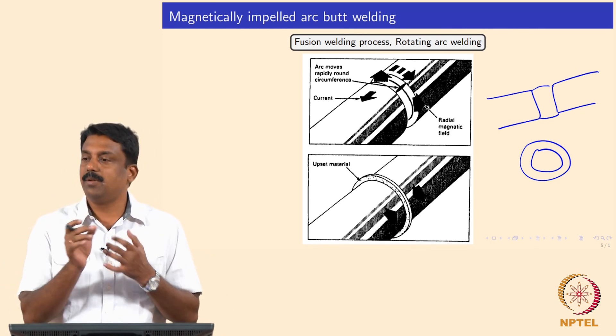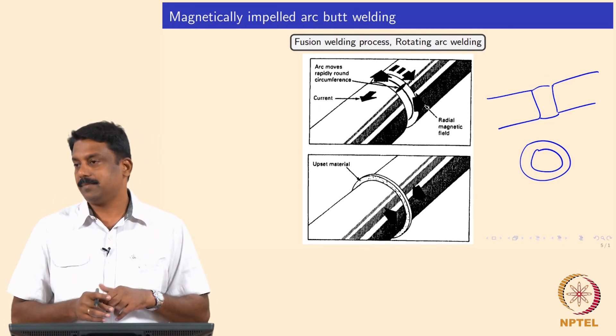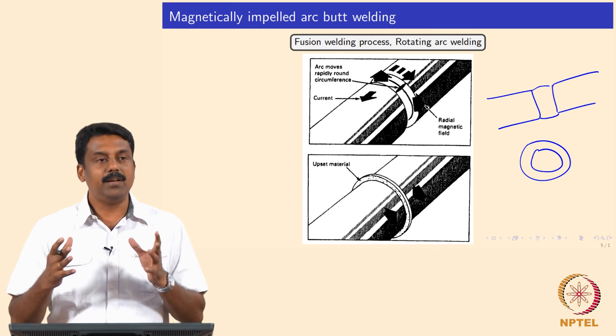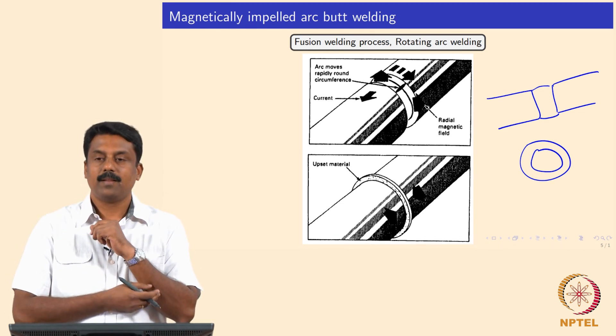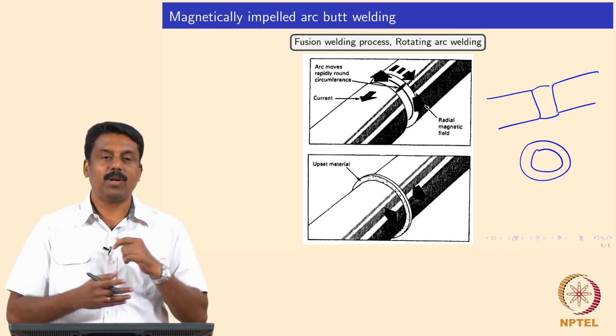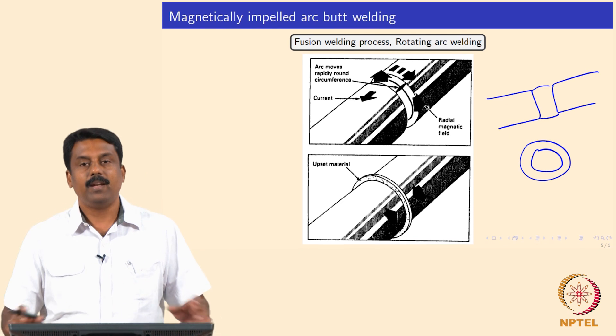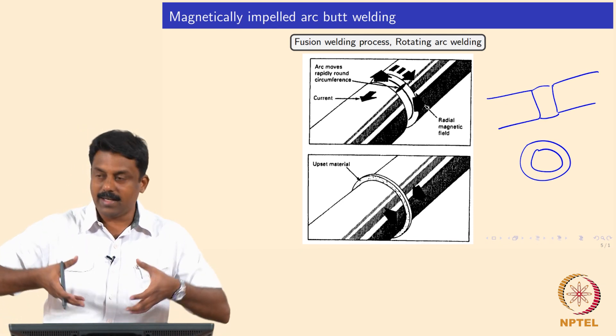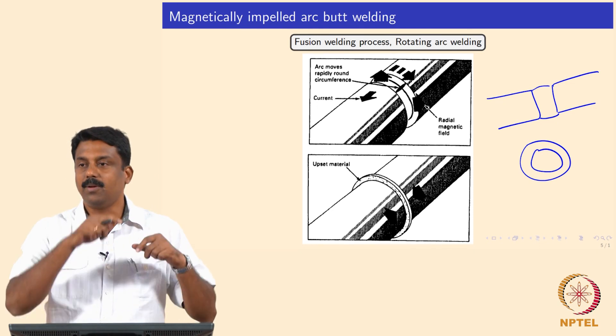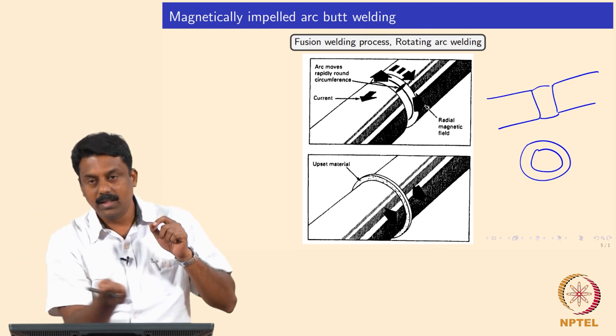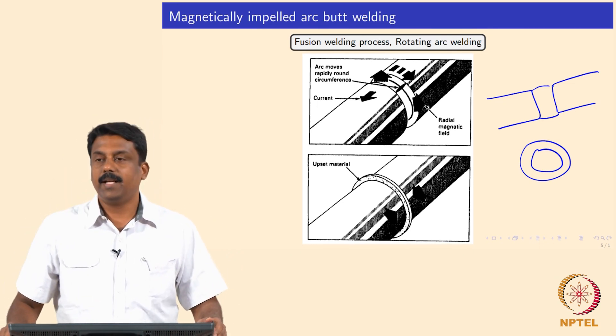The centre thickness will never melt. The heat may not be conducted, and if you want to melt you will have to keep it for a longer time, so productivity is lost. Then you will have to strike more current and spend more energy. So if you attach a magnet surrounding the arc, the arc can be impelled not only through the thickness but also impelled along the circumference.